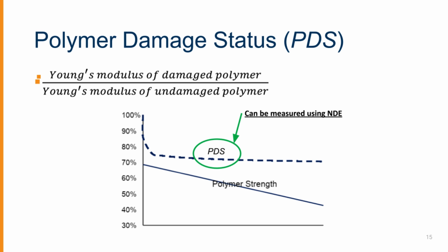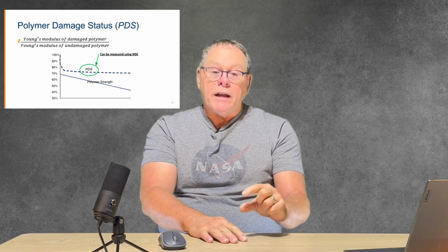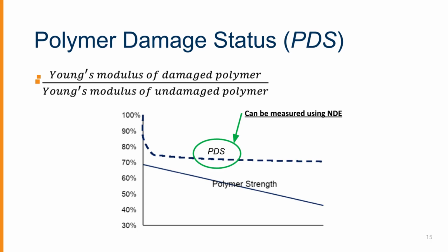What we measure and what we use is something called the polymer damage status. This is a ratio. It's a ratio of the Young's modulus of elasticity of the damaged polymer to the Young's modulus of elasticity of the undamaged polymer. So it's the ratio of how strong it is compared to how strong it used to be. And it's roughly that, because with polymers in particular, and glass doesn't do it this way, we actually will see a reduction in the Young's modulus of elasticity, and along with that reduction, we'll also see a reduction in the actual strain at failure, or the elasticity of the polymer. So both of those combine to show that the polymer strength drops even more quickly than the Young's modulus of the polymer. And this is shown on this chart as the lines start to diverge over time.